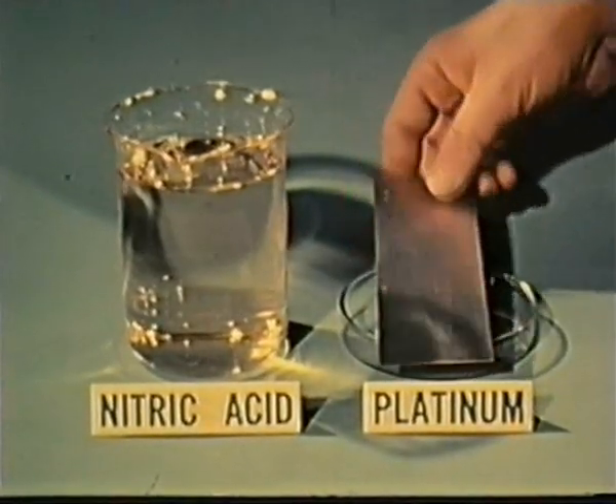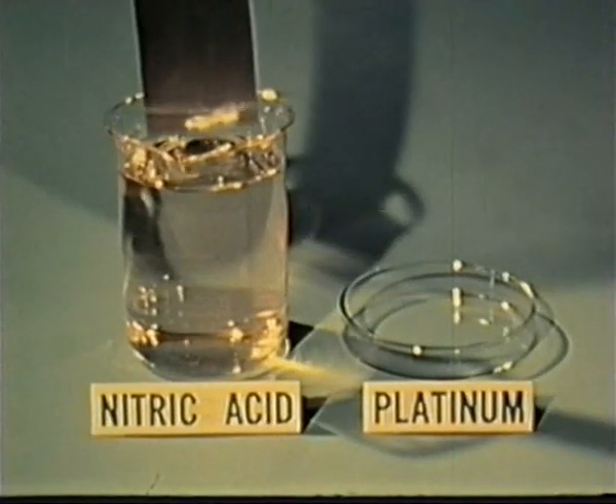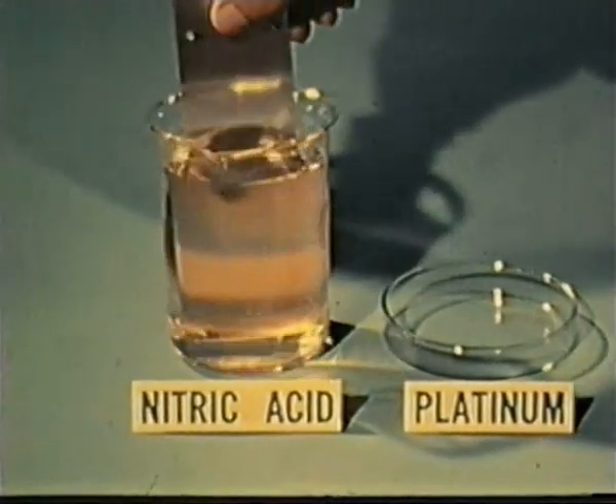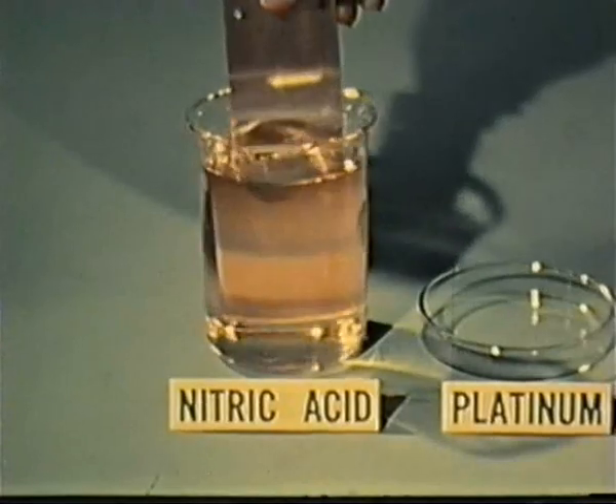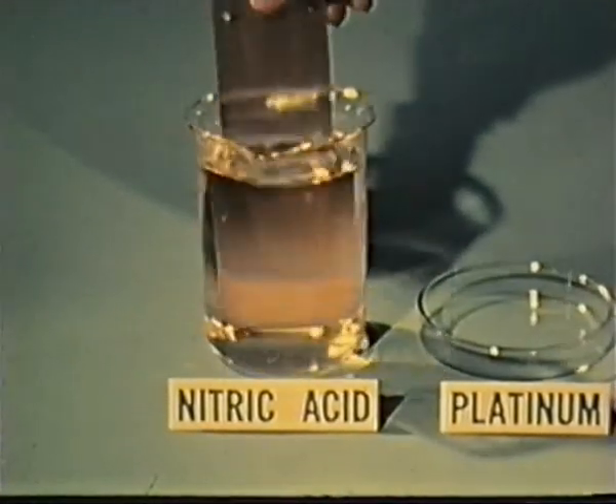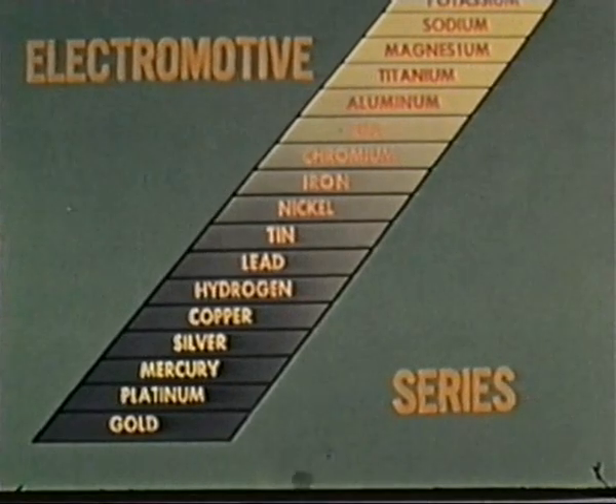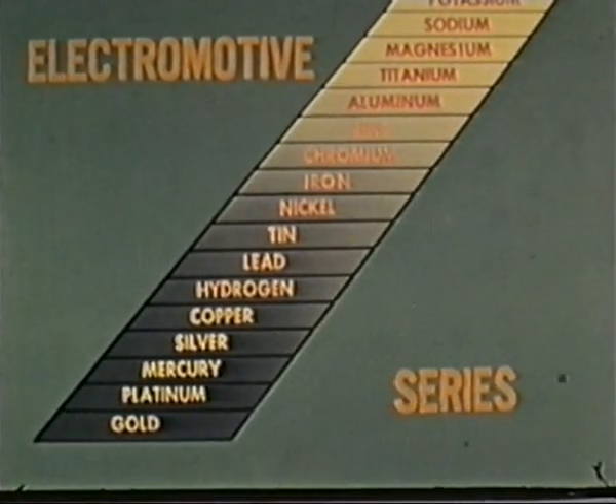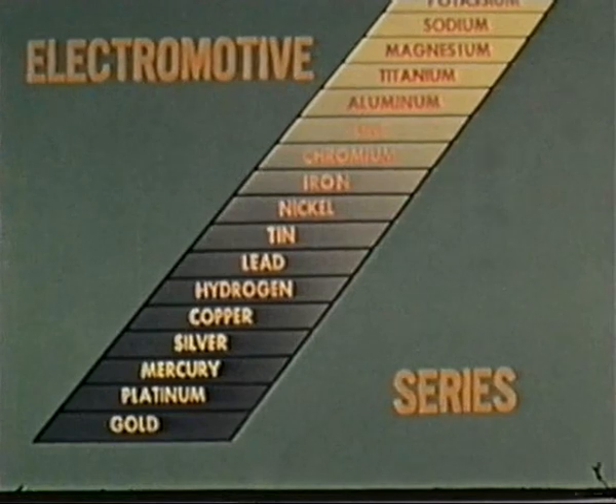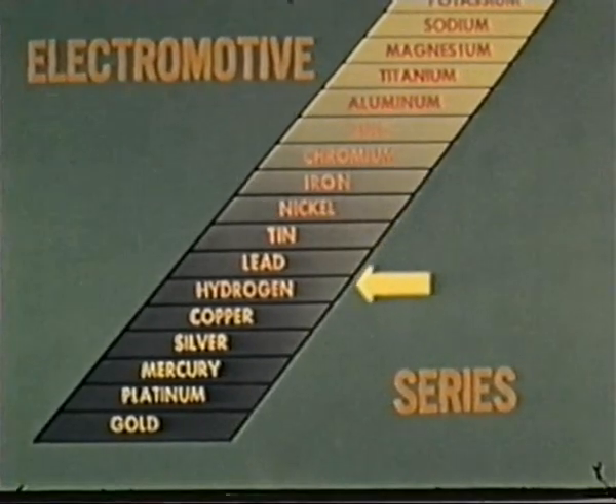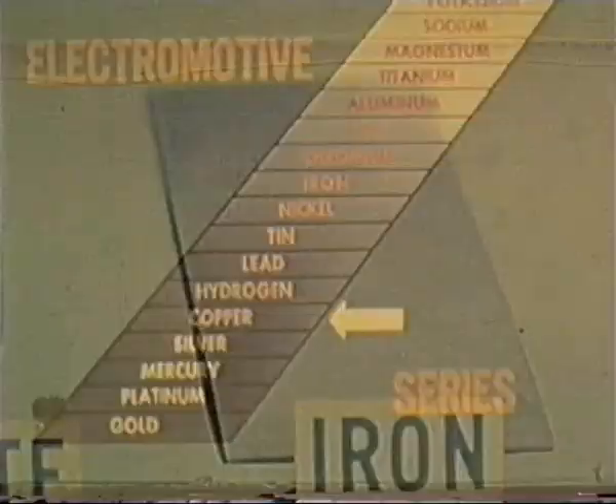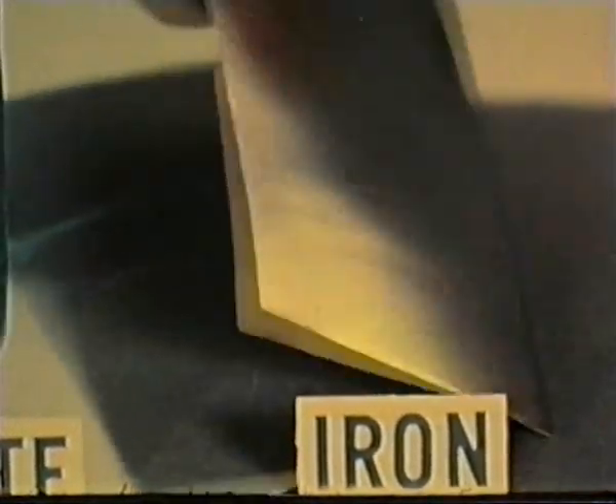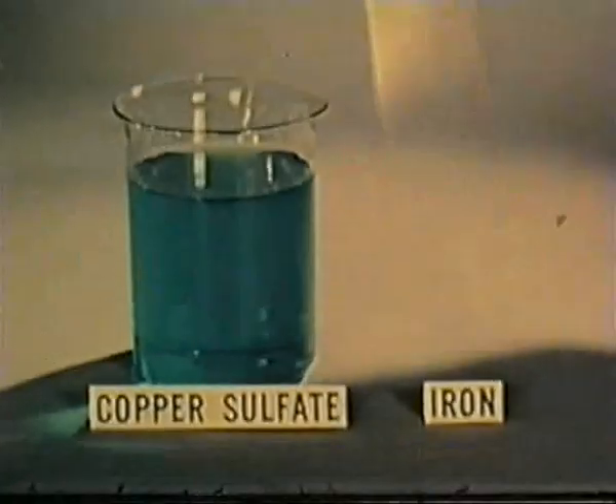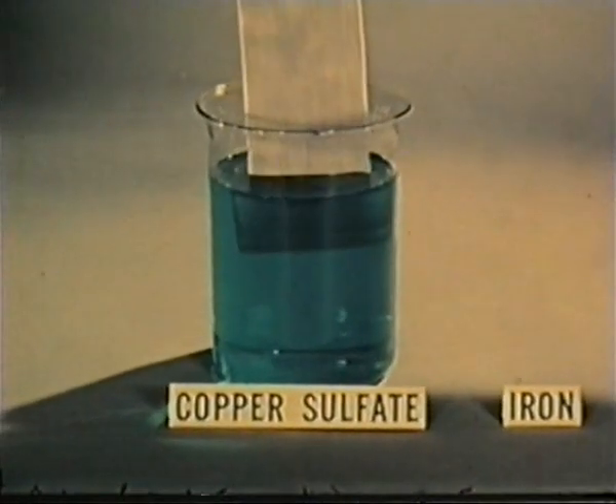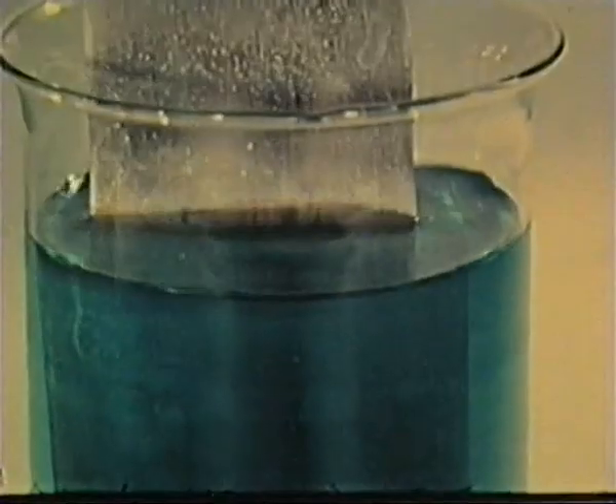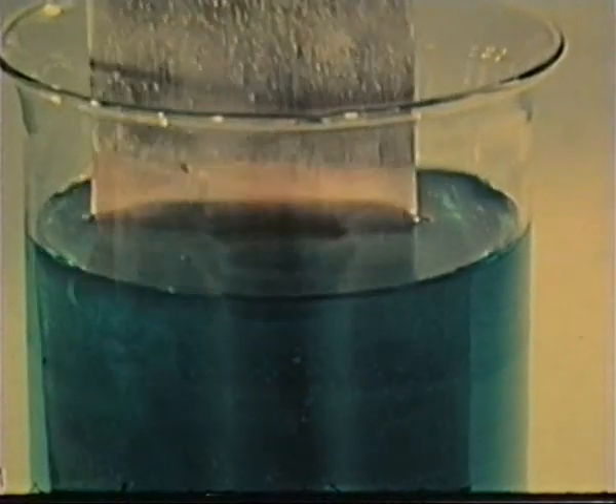Whereas, we can place a piece of platinum in strong nitric acid with no evidence of attack. The electromotive series also shows which metals can displace other metals in solution and suffer corrosion in the process. Any metal may displace one below it in this series. For example, iron can displace copper from solution with the copper ions acting as the acceptors for electrons in the corrosion of iron. The displaced copper appears as a coating on the corroded iron surface.